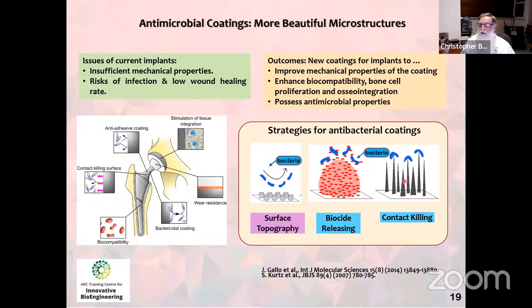Or how do we control the degree of melting? How do we control the degree of melting so that we do get asperities, or we add a second phase so that we get contact killing of pathogens? So again, this is the inverse problem. As a thermal sprayer, these are challenges which are very worthwhile to attack.